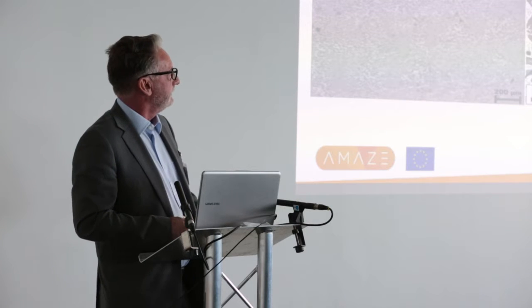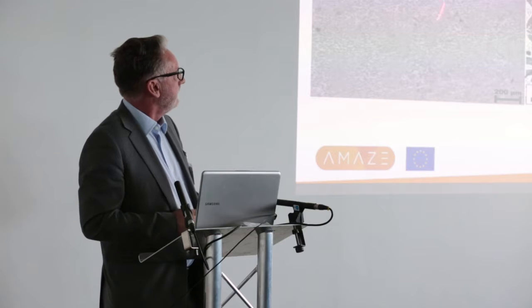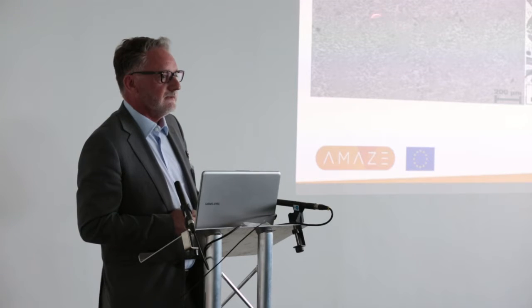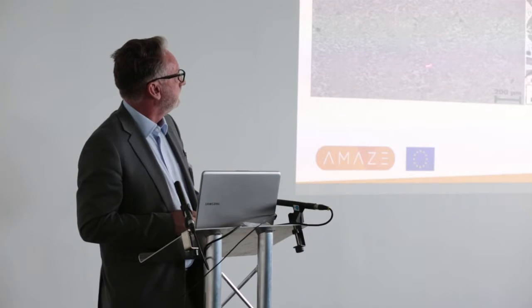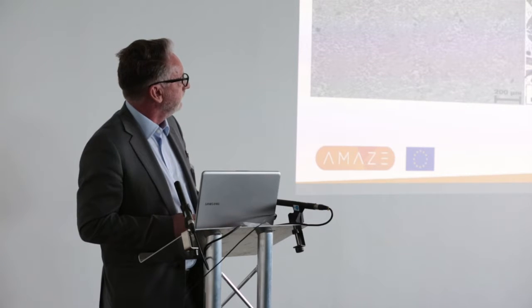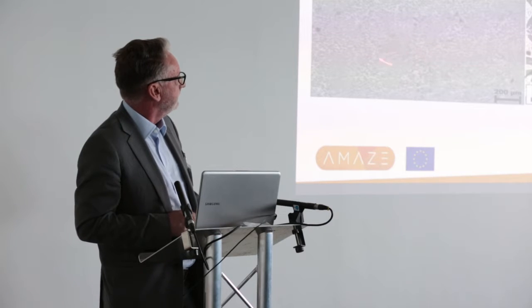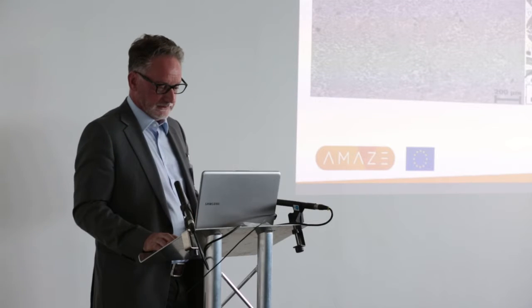As you might expect, the structure is much finer than you get in a cast material. This is a chill cast aluminium silicon with 40 silicon in, and this is our material with 40% silicon added into the same material. Actually, this is a 50 weight material, so this is also 50 weight percent silicon when you add these together. So this is a much finer structure.